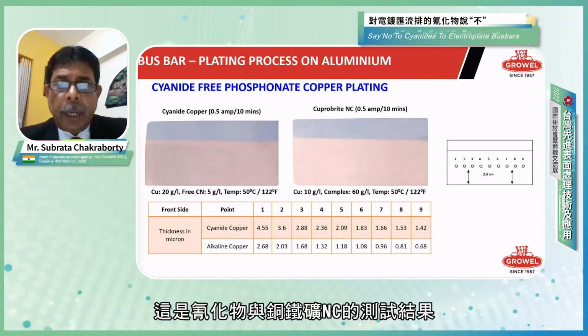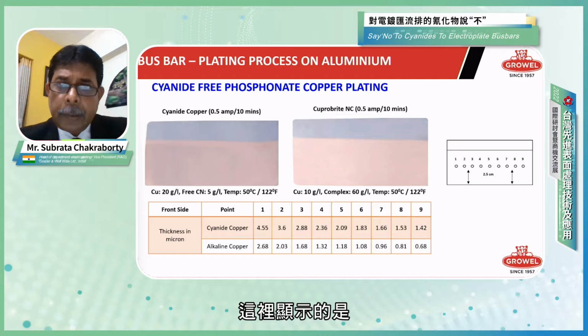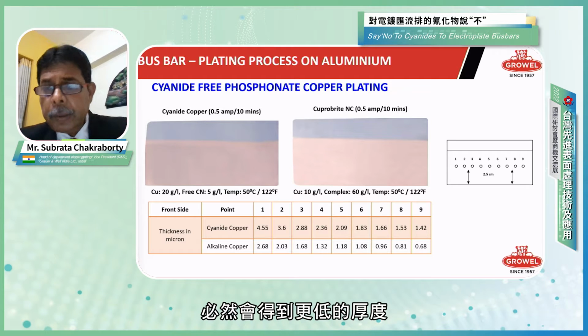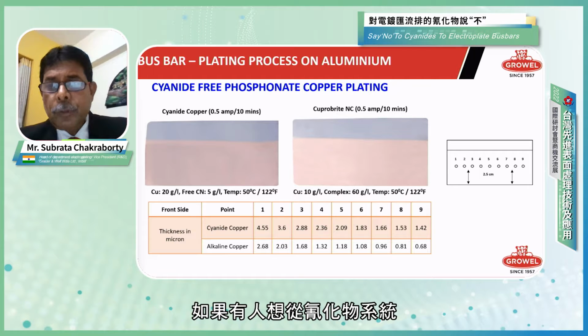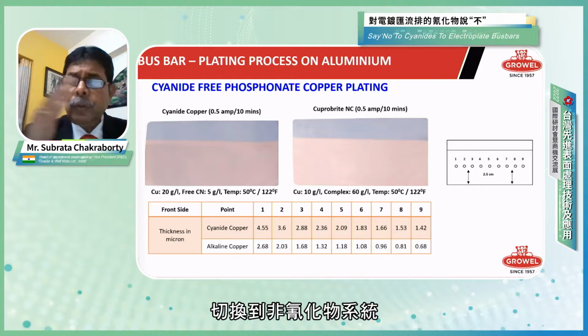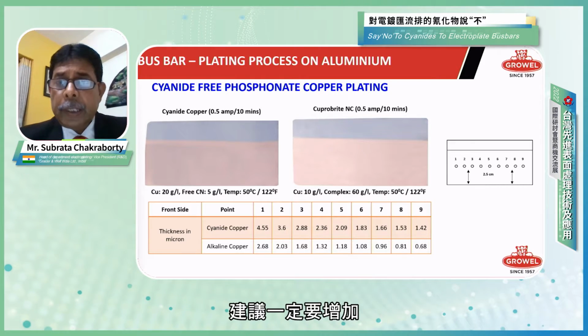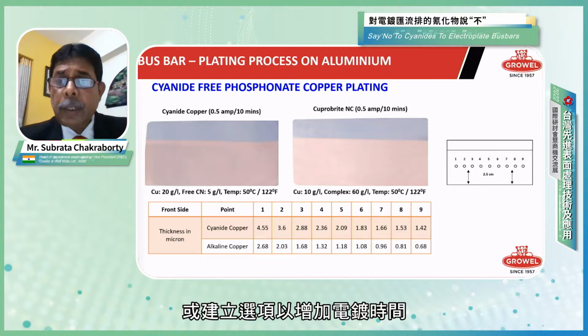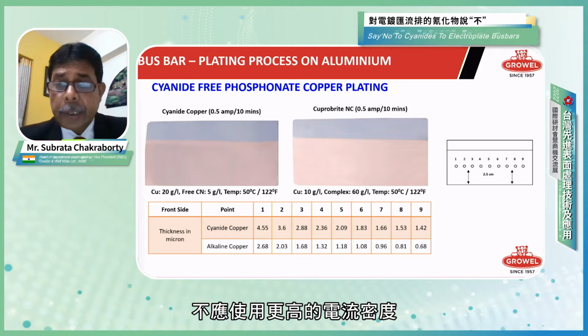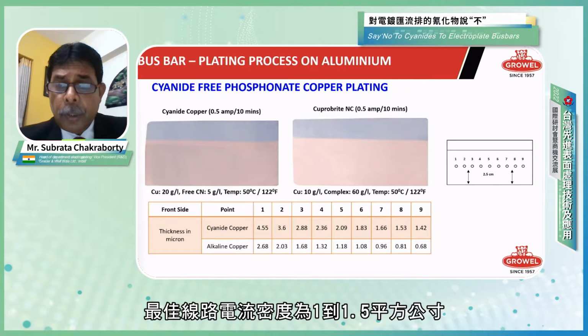This is the Hull cell test results of cyanide versus Cuprobrite NC. We have to tell you here that with the alkaline copper, we are bound to get lower thickness. If anybody wants to switch over from cyanide to non-cyanide system, it is always advisable to increase or create an option to increase the plating time rather than increasing the current density. Current density should not be used much higher; the best inline current density will be 1 to 1.5 ampere per square decimeter.